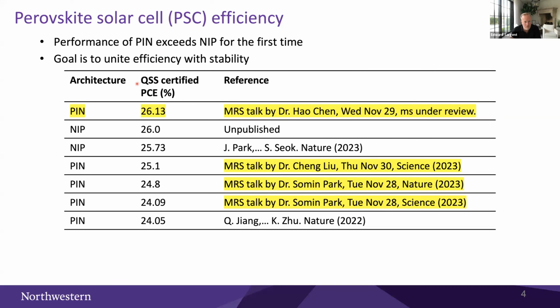You'll see also that we try to emphasize in this talk, and also especially in the headline numbers for our papers, the QSS certified, so the quasi-steady state, just to not get caught up in discussions about whether hysteresis is playing a role. We sit at a stable illumination intensity and at the maximum power point and report the power conversion efficiency under those conditions.